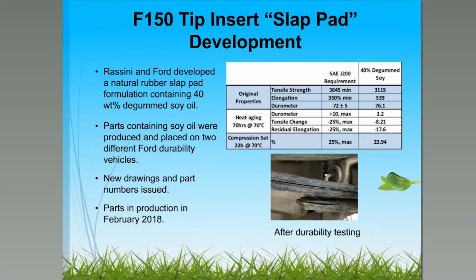The supplier, our supplier partner, Rassini, then took that formulation and tested it themselves, as well as then put it into their proprietary formulation. And they came up with an ideal replacement of 40% of the naphthenic oil with degummed soybean oil. And you can see that the physical properties met all of our specifications. So the parts were produced, placed on durability vehicles. After the vehicles ran through their paces, we found that the part was performing extremely well. So new drawings and part numbers were issued.